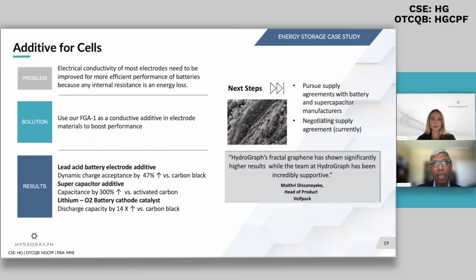And our graphene is a good electrical conductor. So by just putting a small amount into all these devices, we have shown with third-party commercial operators, when you benchmark against the standard incumbent, which is the carbon black as the conductive additive, we perform way better. If you take the lead acid battery, it's the legacy product, but still we can improve the dynamic charge acceptance rate by 47%, which is typically really unheard of, that kind of performance enhancement in the battery world, which means we can charge the battery very quickly.